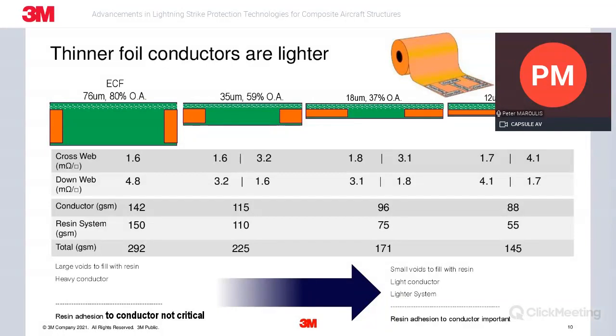And with the limited amount of epoxy that is bled through here on the far right, you would need to start looking at surface treatment on the copper that would help with the adhesion of the whole system. This is not something that hasn't been resolved, but something that needs to be considered for perforated copper foils with a much thinner configuration. Next slide.